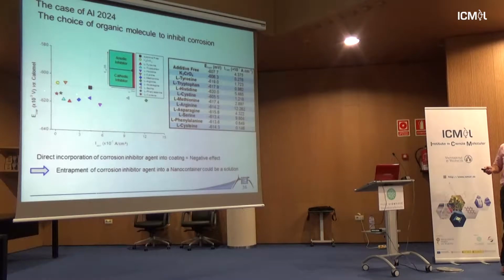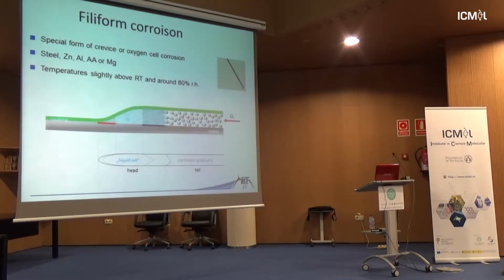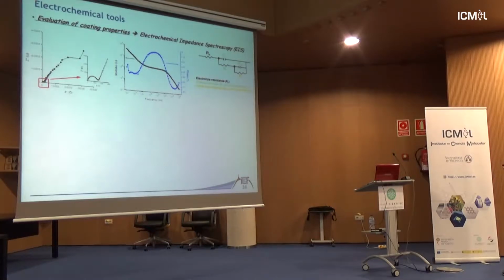So those two were selected to be trapped into LDH, because we don't want them to react with no corrosion occurring. And if they are released, it means that there is corrosion, because in fact the coating has been disrupted. So it's a self-healing on demand. They are dormant, they are sleeping. If the substrate doesn't need them, they are not released, and when you have some breakthrough in the coating, the organic is released. That's nice. So that's a scenario, and of course you have to check all together.